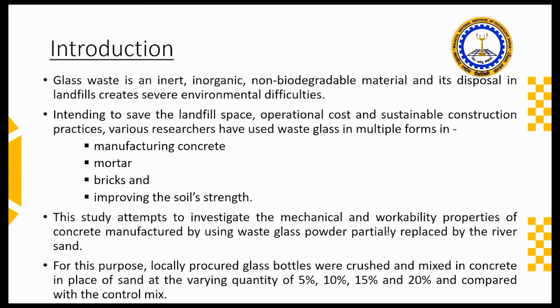As far as our study is concerned, this study attempts to investigate mechanical and workability properties of concrete manufactured by using waste glass powder, which is partially replaced by river sand. For this purpose, we locally procured glass bottles, which were crushed and mixed in concrete in place of sand in varying quantities: 5%, 10%, 15%, and 20%. We then compared the same with the controlled mix, which was 0%.